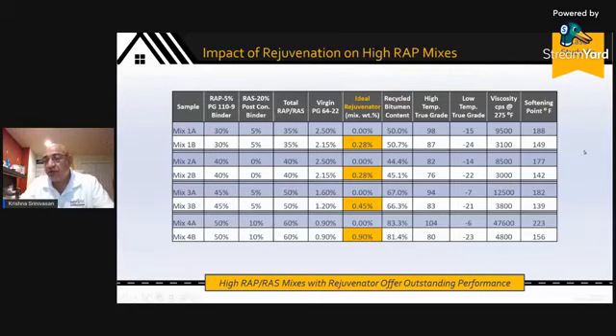You can see the changes in softening point. There should be an additional chart here, simply ran out of real estate. So penetration numbers are also dramatically changed. What you will also see is that as you step down this table, you're going from 30, 40, 45, 50% RAP. And if you look at this column, it tells you how much of your total bitumen content that you're adding to the mix comes from recycled content. In this case, it is 50%. In other words, you are relying on your RAP material to provide about 50% of the total bitumen that is required for that mix. As you step higher and higher, you see higher and higher numbers, all the way up to about, in this case, 85%.